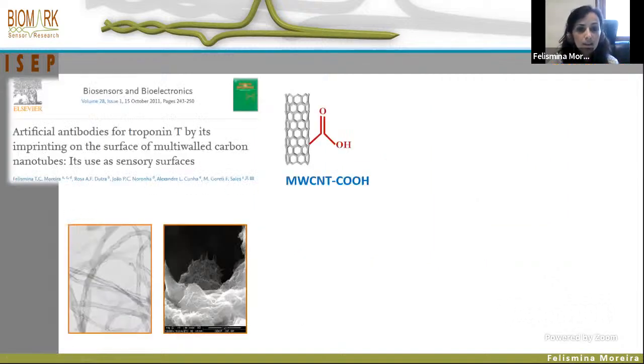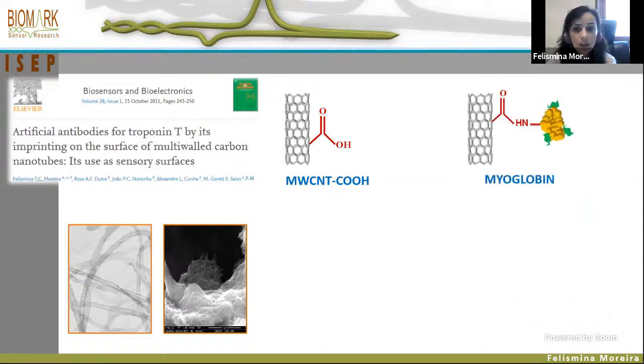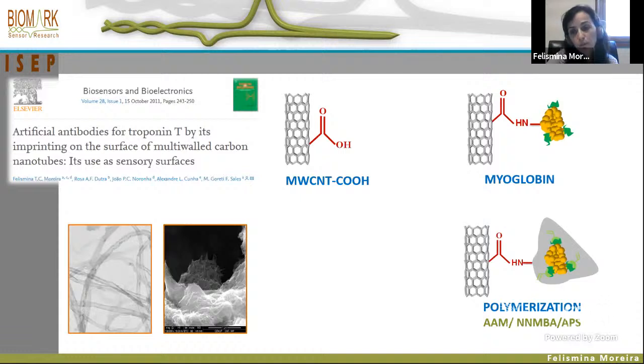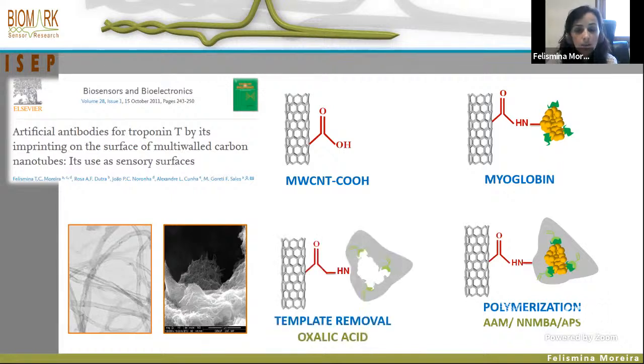Another strategy was to develop one molecular imprinting polymer based on a hydrogel on top of carbon nanotubes. The first step consists in modification or oxidation of the carbon nanotubes for the following covalent attachment of the protein. The polymerization was performed with acrylamide as a monomer, bisacrylamide as a cross-linker, and ammonium persulfate as initiator, and the template removal was performed by means of oxalic acid.